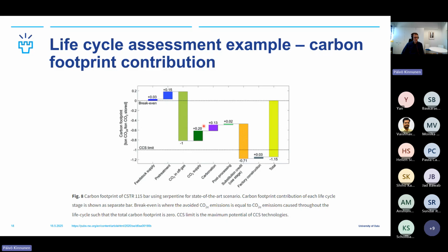Then you have to account for the CO2 supply. So you're actually capturing the CO2, which you get a penalty for. And then carbonation also costs some CO2, as well as post-processing. But then here, what they considered is, I guess, a theoretical example of replacing cement. And then you get another substitution credit when you're replacing CO2 emitting materials. So you get this substitution credit, and then you have to take into account the factory construction.